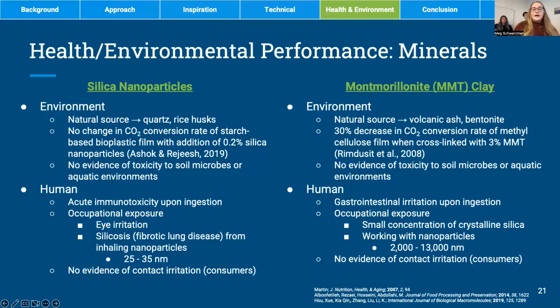For montmorillonite clay, similarly, starting with the biodegradation metric, we looked at a study that looked at the biodegradation rate of a methyl cellulose film that was cross-linked with 3% MMT. And while this film was completely biodegradable, with the addition of MMT, there was a 30% decrease in the rate of carbon conversion.